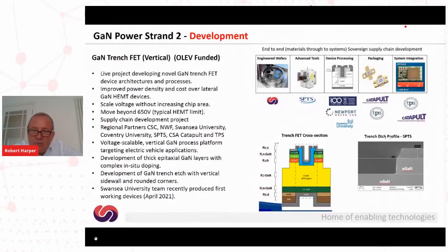And again, we've done a lot of work with SPTS to optimize the profile. The profile there is pretty much optimized. It has a nice rounded corner at the bottom, which is highly desirable because it removes a high field point from that corner. If you micro trench into that corner, you can end up with premature breakdown of the device. So a lot of good work's been done within this project to optimize the trench profiles, to optimize the epi doping, to give us the desired electrostatic control of the transistor.